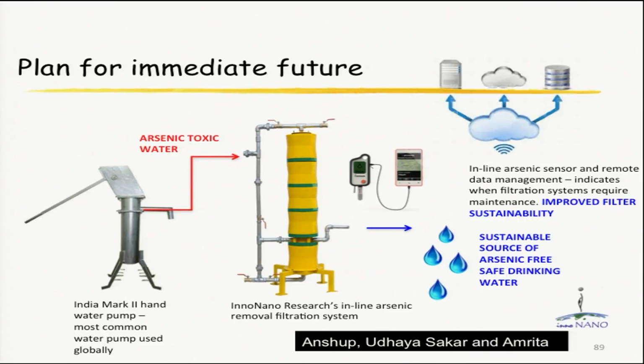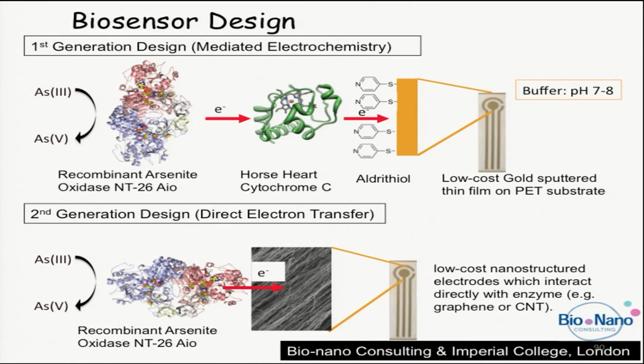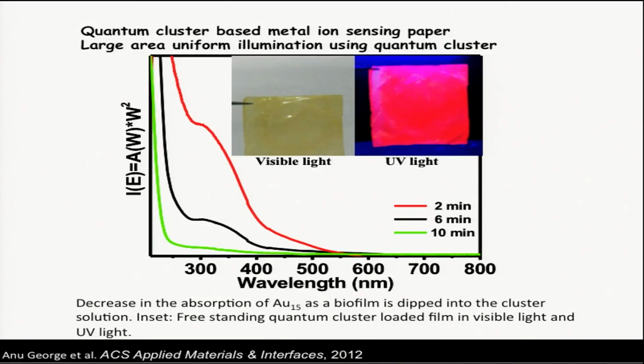Well, it is possible that with a new kind of science, it is possible to detect arsenic in water and send it through mobile. And that is there because new nanomaterials can transfer arsenic 3 to 5 transformation, and in this process, the release of 2 electrons can be effectively taken to electrodes by a process called direct electron transfer. And by this process, we may be in a position to go down to about 2 parts per billion of detection. Today, it is impossible. And we are in that process today.